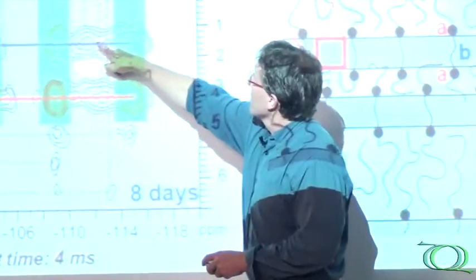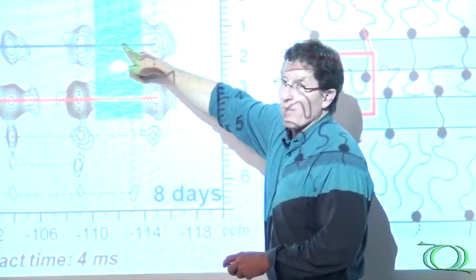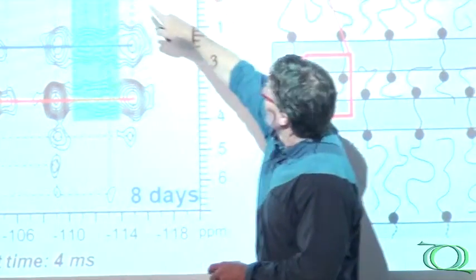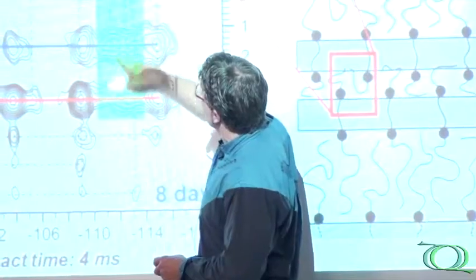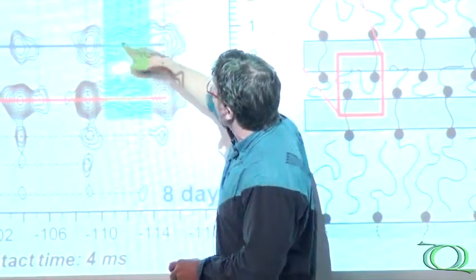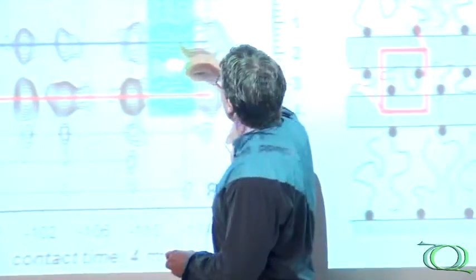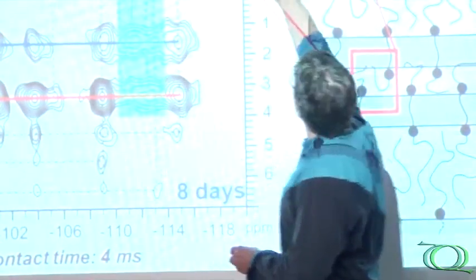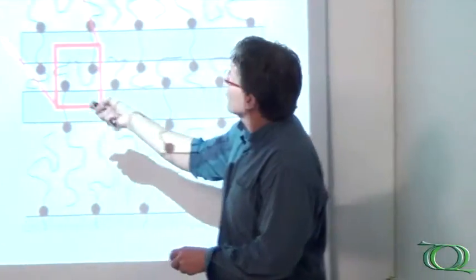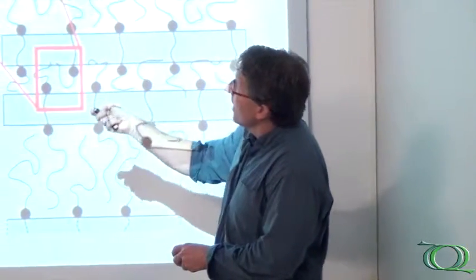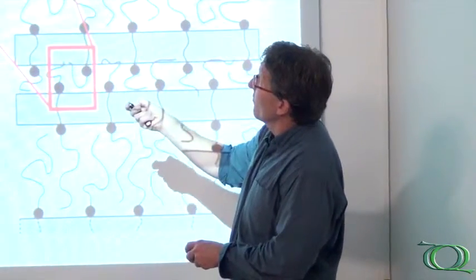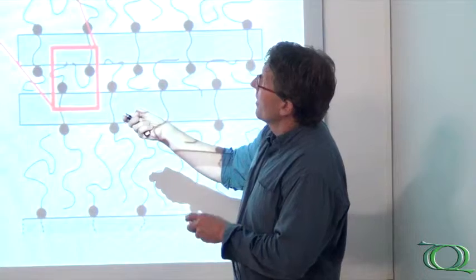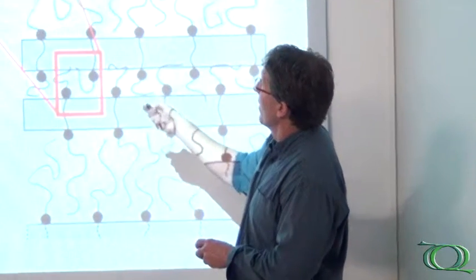Now look at this. This is the same spectrum but now with this species. So now this is the ZSM5, this crystallizing structure, and those also are the ones that are strongly interacting with these head groups and not the others. So this is a sign that you've got this zeolite structure which is being templated and directed by these different structure directing groups in this surfactant in a very unambiguous molecular way.